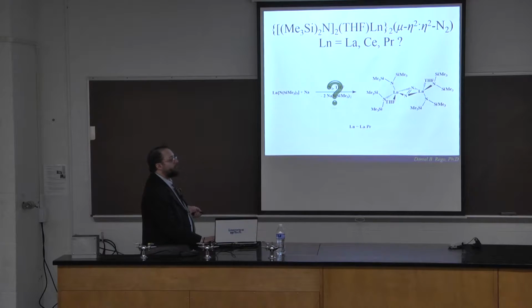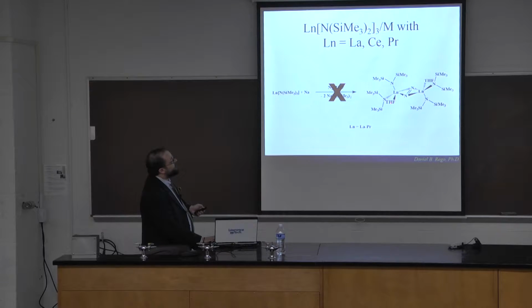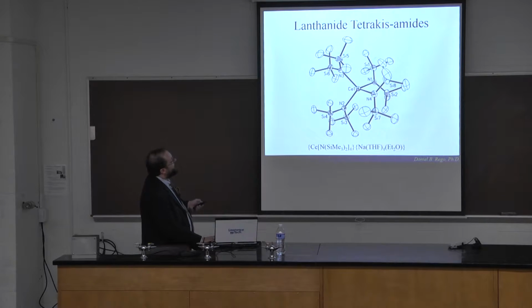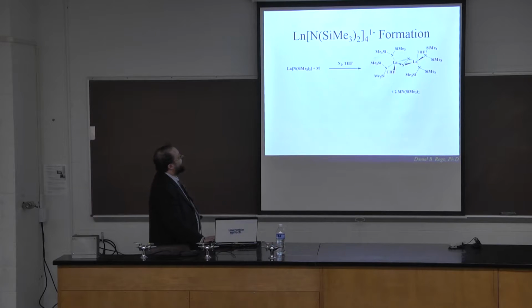So I noticed I didn't mention the early lanthanides, lanthanum, cerium, praseodymium, kind of a question of whether we can make this or not. Turns out we couldn't isolate a crystal structure of this, and the reason was that we were actually getting this compound. This is actually overall an amide, so 3+ cerium with these trimethylsilyl amides, which are 1- each, so overall 1-, and sodium as a countercation. What turns out to be happening is as soon as we start forming this compound here, the byproduct is an alkali metal amide, and this is combining with the starting material to form these tetrakis anions. So because of that, we're eating up the byproduct and starting material, so we're not really getting a lot of this.